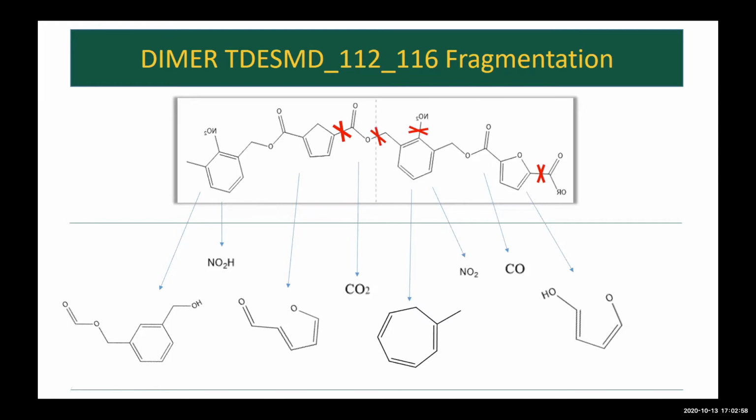These red X's that I'm showing are meant to be just the first set of decompositions. For example, as you can see here, the red X shows the bond had broken between the oxygen and carbon and these two carbon bonds, and it generated CO2. NO2 had broken off. And over here, due to the periodic box, this CO2 group had been able to connect back to the benzene ring, which was originally part of the nitrobenzyl group. Over time, all the other changes that you see had occurred, but I just wanted to show the initial or primary mechanism.